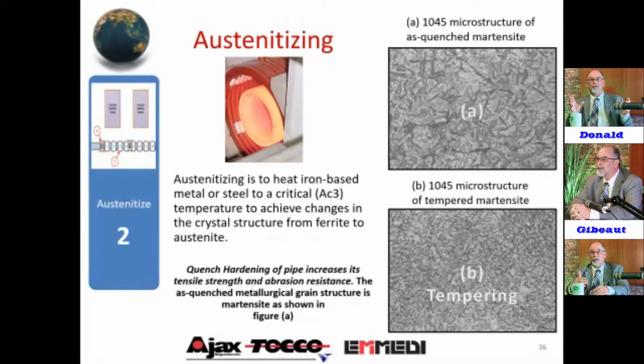The furnace lines are a lot longer, a lot more costly because they heat on a surface and they conduct all the way through. Again, even though we're shallower below the magnetic Curie point for tempering, we're still inducing current at a depth of penetration, so we can put more energy into it without overheating the surface and heat it more rapidly. And we have found we go a little higher in temperature in the temper, and we match the same metallurgical results, or at least close enough for acceptance throughout. Now, we have done preheaters on temper for furnaces for people that want that and feel that they make a better product that way. So we work either way.